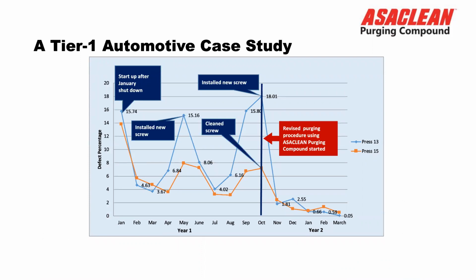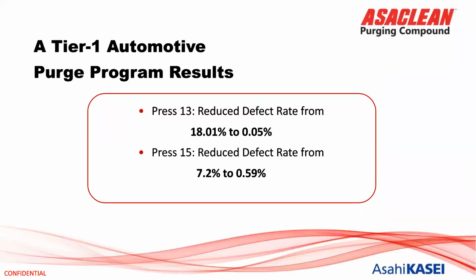On this chart here, everything left of the vertical black line, where it says revised purging procedure using Asaclean started. As you can see, after every startup, there is a period of lower scrap, but it doesn't really last long, and you have a defect percentage that is in flux. It's constantly coming back up. You install a new screw, okay, you lower scrap temporarily, but here goes the scrap again. When you use an effective purge program that successfully removes layers and actually removes the polymer, then you're going to be looking at these consistent lower scrap rates, as you can see to the right of the line. Pretty drastic improvement there, 18 to 0.05, 7.2 to 0.59 at this automotive injection plant.